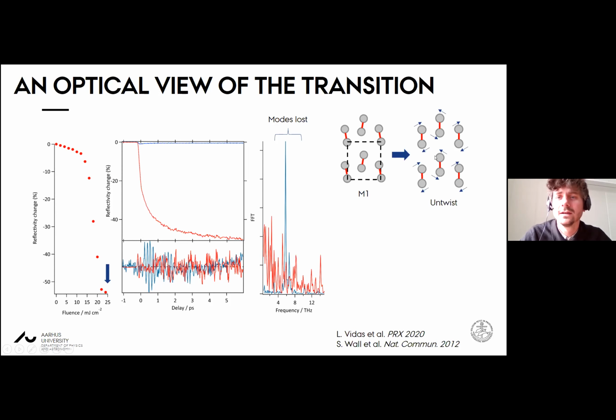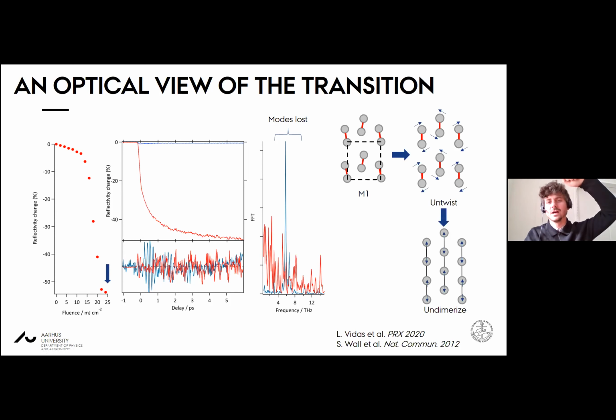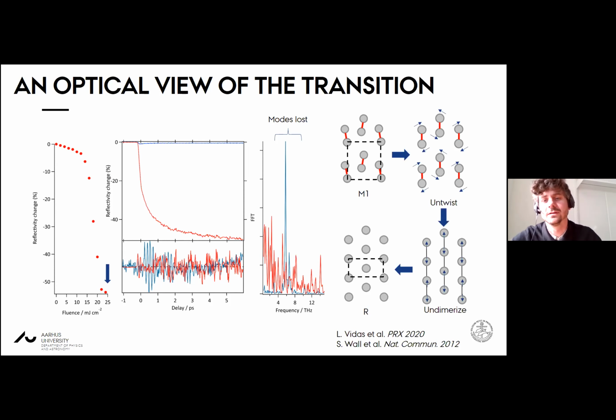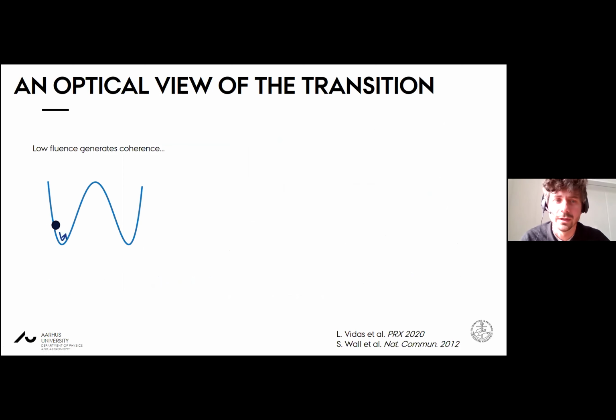Okay, so one possible scenario is that they undergo a transition along these lines. We can see if we carry on the twisting motion from a small amplitude to a larger amplitude, we'll eventually align all the vanadium dimers. We can also undimerize, and if we undimerize by a significant amount, we can map the structure back onto the rutile phase. And of course, this untwisting and undimerization doesn't have to go in a stepwise manner, most likely they go simultaneously. And the question is, are we doing this loop from the M1 to the R phase in this continuous motion that I suggested here, or is the system taking another pathway?